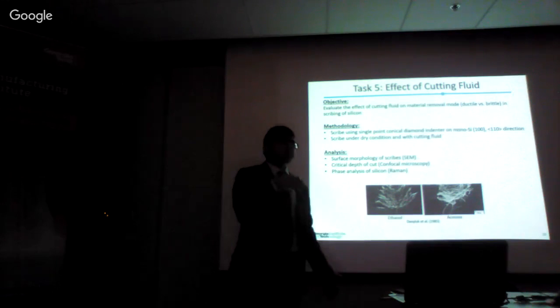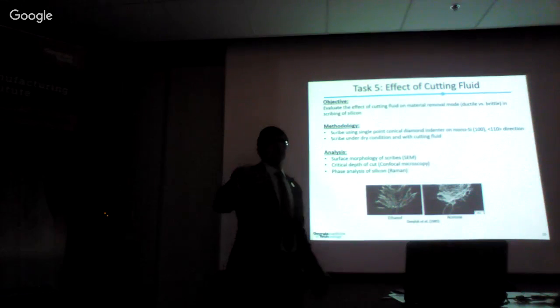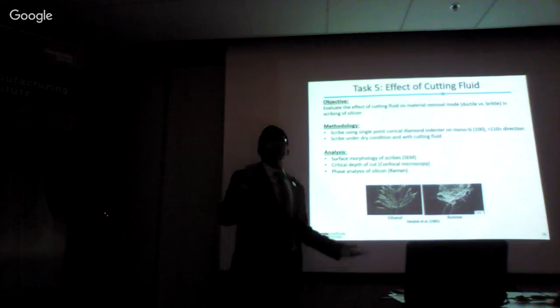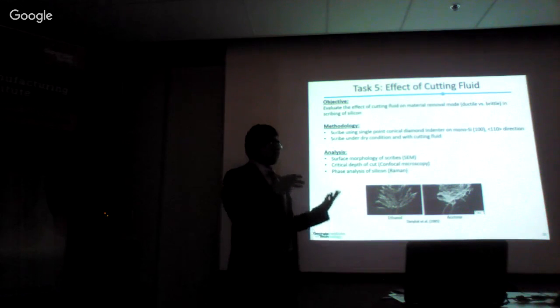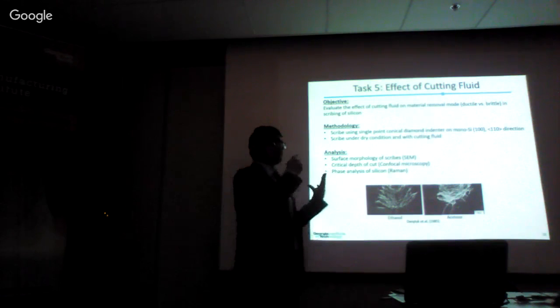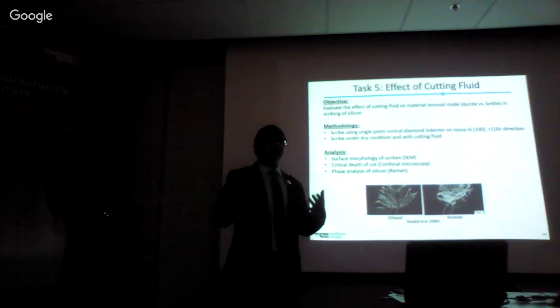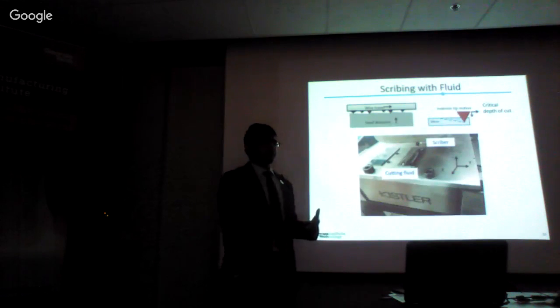So some prior work in this space had been done by Dr. Danyluk's group some time back, where they found that different liquids in contact with silicon, like ethanol and acetone, gave different wear rates of silicon when scribed under identical conditions of load and the same indenter. So fluids are known to have an effect on the material being scribed. Here we want to find out if the cutting fluid, which is actually used in industrial operation, can have any effect on the ductile mode material removal.